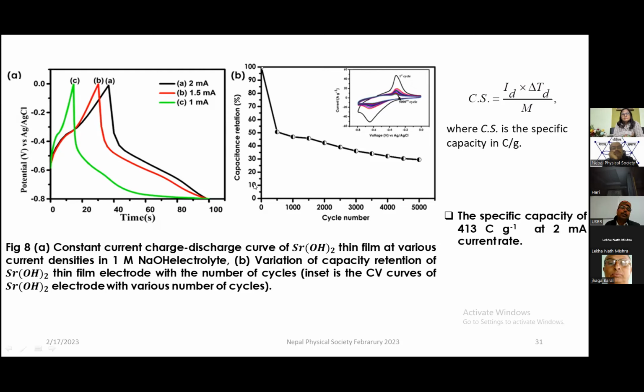And for capacity, if you want to use it as a capacitor, then one has to find out the capacitance retention with the number of cycles. We have analyzed up to 5,000 cycles here, that is 5,000 times charge and discharge. One can see that up to 500 or so, its capacity is decreasing to 51, and then up to 5,000 it is retaining more than 30. So more than 30% of the capacitance is being retained. So this can be used for supercapacitor application.